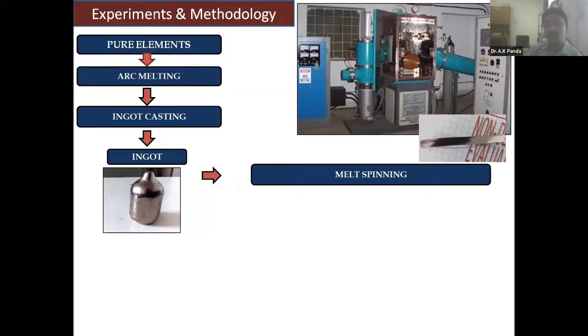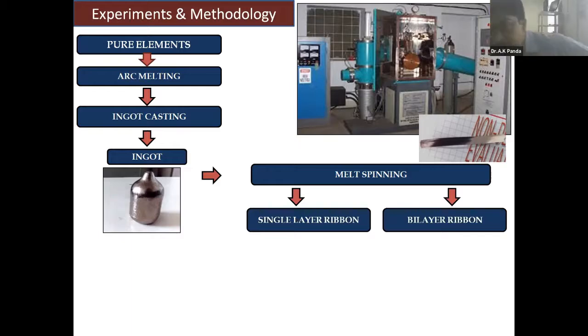Secondly, we also work on further modification in the processing. One is the melt spinning system that we have, and on the right side that you see is a copper based, very high speed rotating wheel. You melt the alloy using induction melting, and then eject it onto the rotating wheel, and you get ribbons. It can be either a single layered ribbon, I mean a ribbon of only one alloy, or a bilayered ribbon where we make ribbons of two alloys.